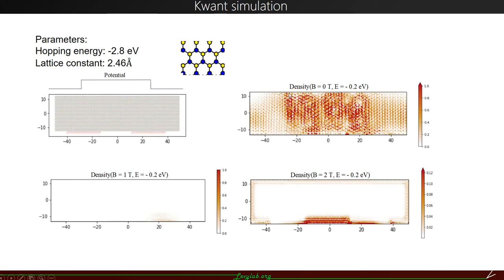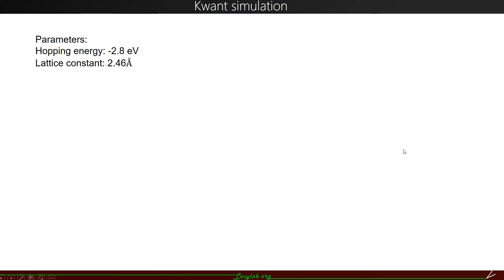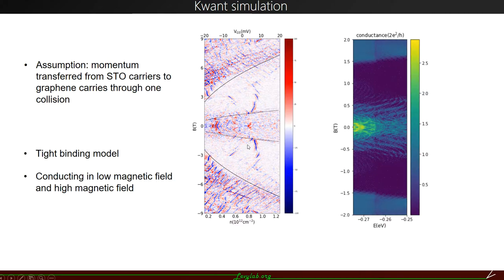And here we put the density plot of the wave function at some fixed chemical potential, and we vary the magnetic field. So we can see at 0 Tesla, the wave function is distributed in the whole device, and as we increase the magnetic field, the wave function is localized at one graphene lead. And as we keep increasing the magnetic field, edge states start to form, so the conductance can exist from one lead to the other, which corresponds very well with our experimental data.